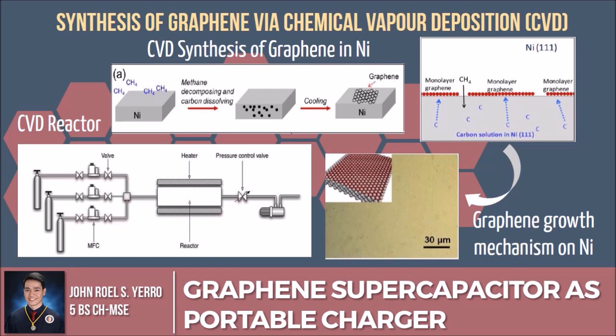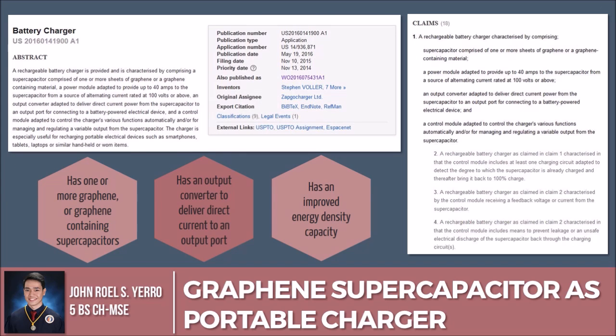In general, polycrystalline nickel films are first annealed in an argon-hydrogen atmosphere at 900 to 1000 degrees Celsius to increase grain size and then exposed to a hydrogen-methane gas mixture. In this step, hydrocarbon decomposes and carbon atoms dissolve into the nickel film to form a solid solution. Finally, samples are cooled down in argon gas. Since nickel has a lattice similar to the densely packed hexagonal lattice of graphene, nickel's surface can serve as an excellent lattice-matched substrate for graphene growth.